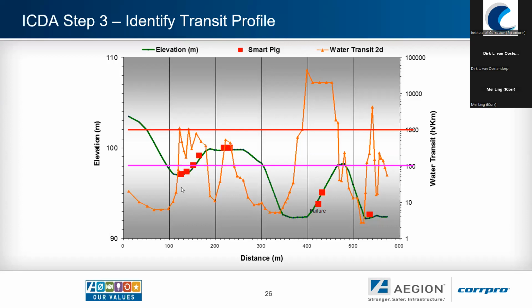And so you can see that in some of the cases, we were looking at water residence times in tens of hours. Whereas in other areas, we were in the 12 to 15,000 hours of residence. And so, interestingly enough, when we projected out known smart pig indications, ILI indications in this same area, we could see that this lined up very well with the areas where we had very high water stagnation, where the water actually resided in there for hundreds and thousands of hours of time. So, the confidence there was quite good.